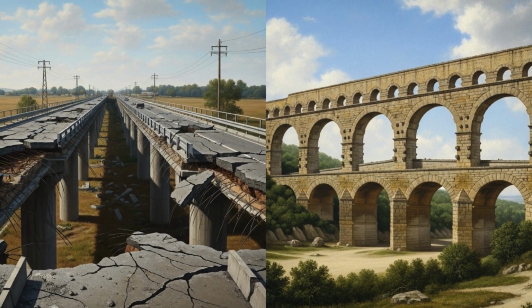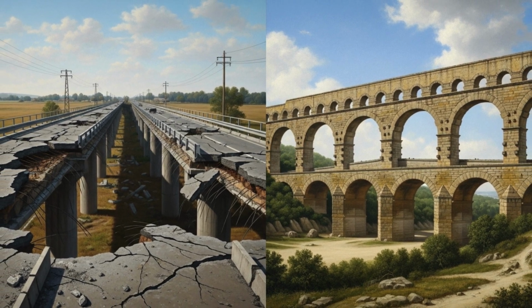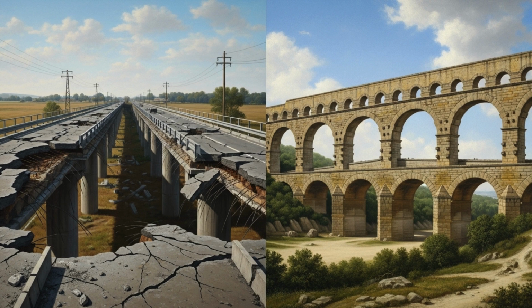So let's get into the actual science. What's happening at the molecular level that makes Roman concrete so special? Research by Marie Jackson and colleagues used multiple techniques: electron microscopy, imaging concrete at nanometer scale; X-ray diffraction, identifying mineral composition; Raman spectroscopy, analyzing chemical bonds; synchrotron radiation, high-energy X-rays revealing crystal structures. What they found was remarkable. Roman marine concrete contains aluminous tobermorite, a mineral that's extremely rare in nature and exceptionally stable. It forms at temperatures of 50 to 80 degrees Celsius under pressure over long time periods. The Romans weren't creating it intentionally. They didn't know it existed, but their mixture of lime, volcanic ash, seawater, and time created the perfect conditions for it to form naturally.